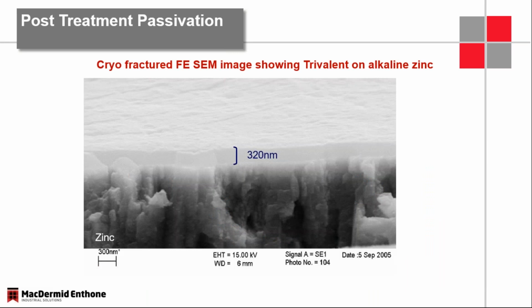So what we're left with after the process is, on average, the most popular trivalent iridescent passivate films, which are going to be about 250 to 350 nanometers. So they're very, very thin. They're also, like I said, gelatinous. They can be scratched. They need to be cured for 24 hours. They need to be dried properly. So care must be taken in the formation of this passivate, as well as bulk processing after the passivate has been formed. It scratches very, very easily.